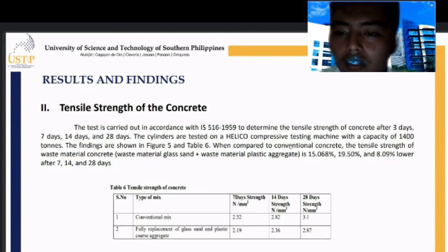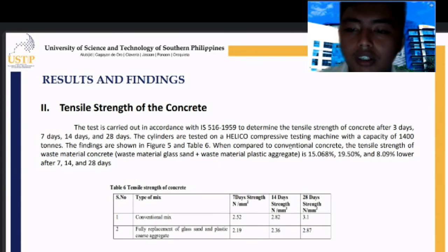And for the tensile strength of the concrete, the test is carried out also in accordance with IS 516-1959 to determine the tensile strength of concrete after 3 days, 7 days, 14 days, and 28 days. The cylinders are tested on a compressive testing machine with a capacity of 1,400 tons. The findings are shown also in the table below, in which the tensile strength of waste material concrete is 15.068%, 19.50%, and 8.09% lower after 7, 14, and 28 days. And that is our results and findings of our study.